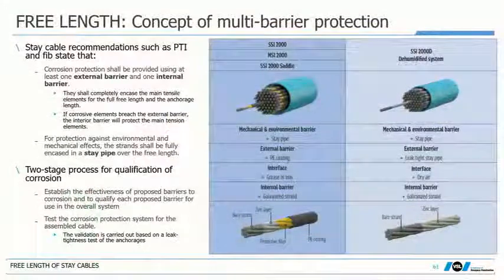Let's talk about cable free lengths and corrosion protection. Today, most recommendations require multiple layers of corrosion protection. And we're talking about two nested barriers, and the interstice between these two barriers is filled with a hydrophobic medium. So this is a typical FIB concept, where the two barriers are here the PE coating, here the zinc, and in between you have this wax or this grease, whatever hydrophobic medium.